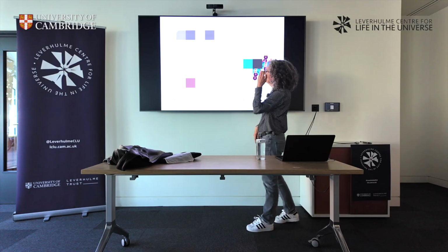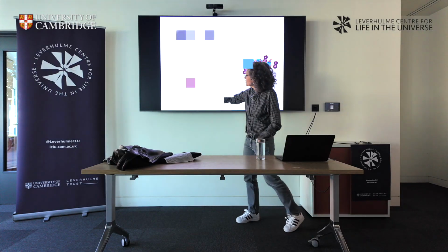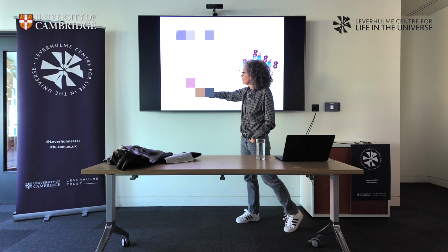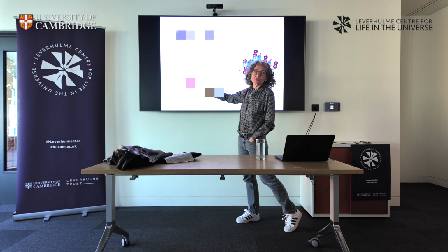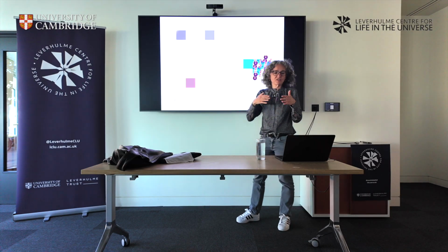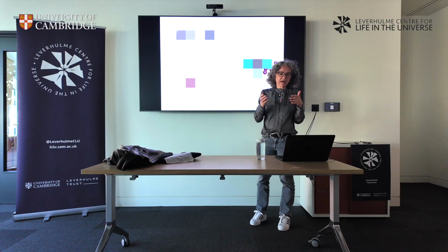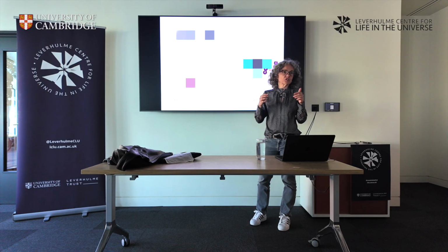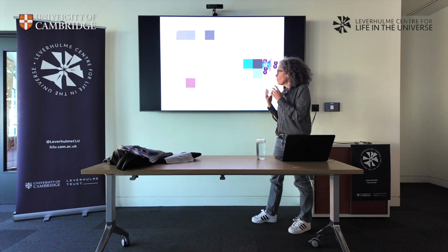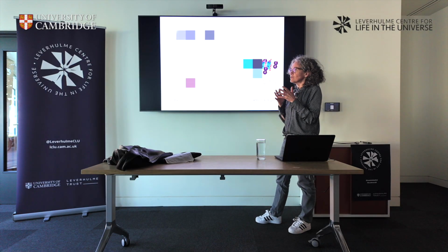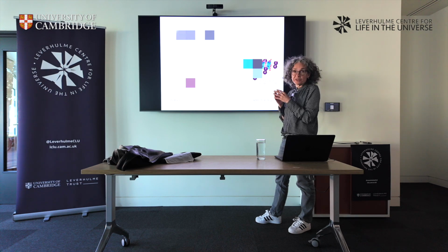When you do X-ray absorption spectroscopy and you see a distance here, it's not the real distance. It's not like X-ray diffraction. In X-ray diffraction, you fit a distance, and it is the real distance. Not in X-ray absorption spectroscopy, because it depends on the exact path followed by the X-rays in your sample, and there can be multiple paths. So it's more complex than that, and you need to have some starting model structure to fit it.